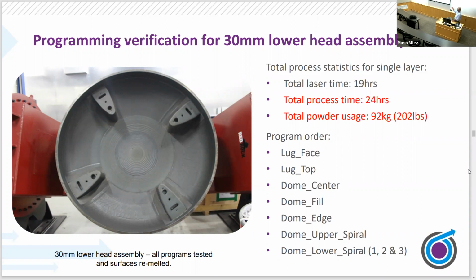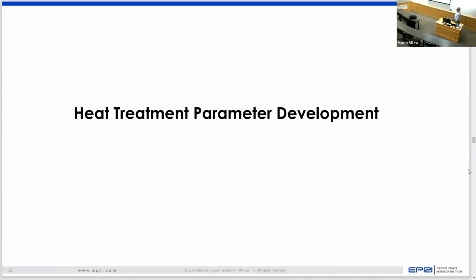Another big changer is we only used about 200 pounds of filler material on this. The small modular reactor that we're talking about will have enough surface area. Basically, it will be the same surface area as 2 Olympic swimming pools because it's clad inside and out. So by reducing that overall amount of filler material, you're reducing cost, you're reducing the overall amount of time that you're trying to apply that cladding to. So that's 3 of the technologies we've worked on.